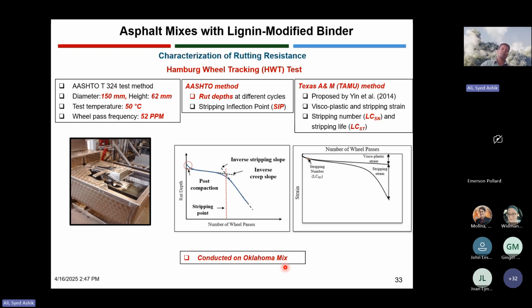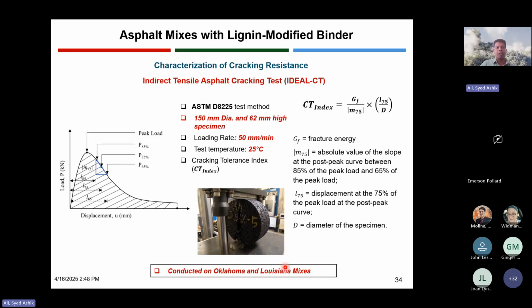We separated the work: Oklahoma evaluated some properties, and LSU evaluated some other properties of asphalt mixes. We wanted to see how the lignin modified binder will impact the cracking resistance. The test we used for that purpose was the IDEAL-CT. The ASTM D8225 method was used. After doing the test, we calculated the CT index value of the asphalt mixes using this formula. I'm not going into the details of this formula here. We'll talk more about the results.